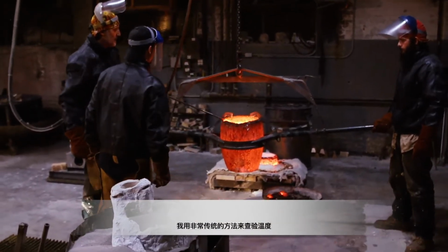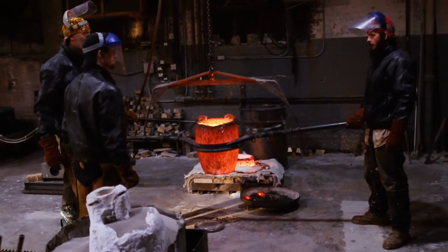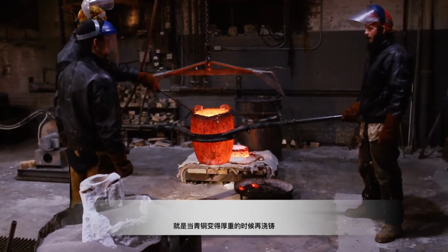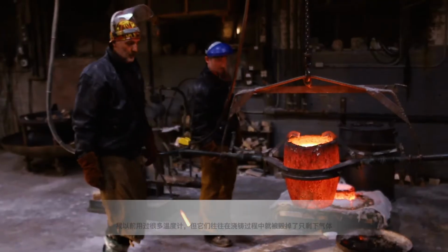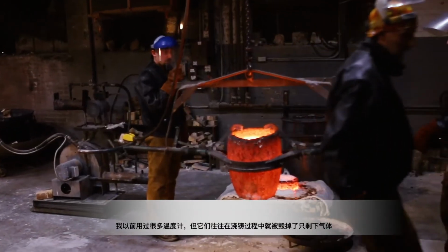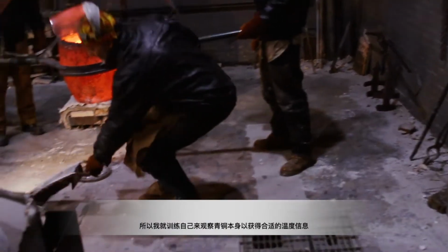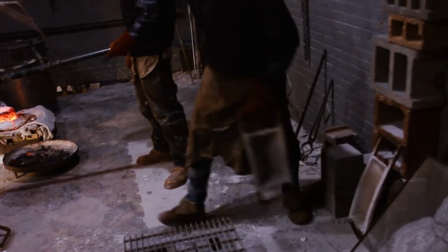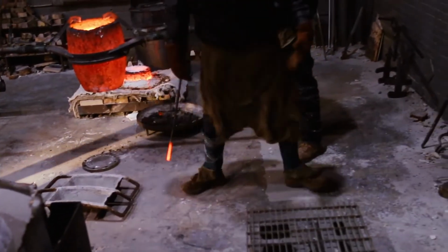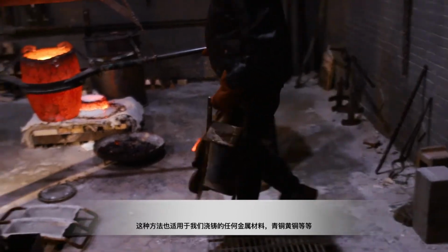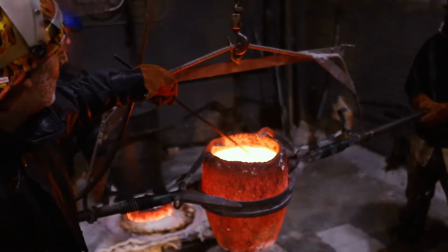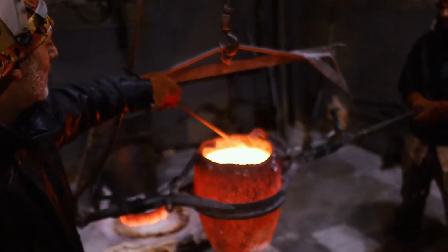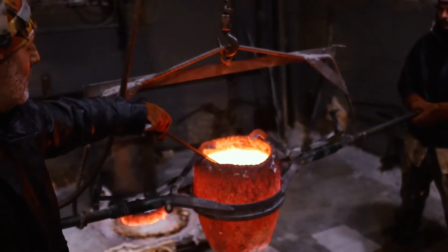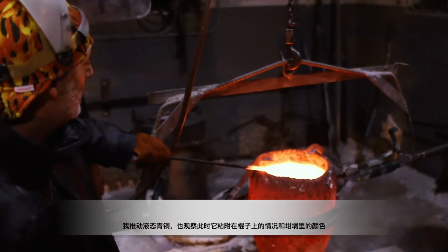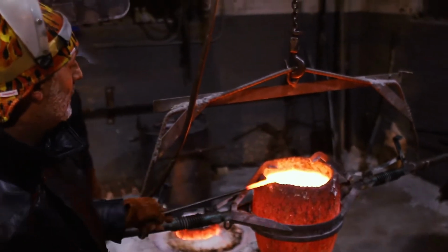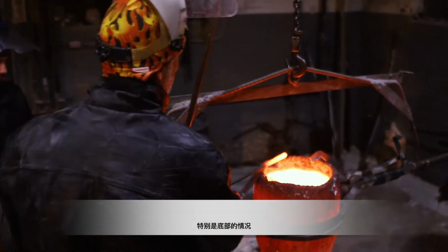And I use a very old-fashioned way of telling the temperature, and that is when the metal behaves thick, then pour. I've tried various pyrometers, and they break in the middle of a pour, and you're left guessing. So I've just kind of trained myself to pour when the metal behaves a certain way, and therefore that approach works for any kind of metal we're casting, if it's aluminum or bronze or brass. I'm pushing it around, but also I'm watching how it sticks to that stainless steel rod, and I'm watching the color on the crucible, especially at the bottom.